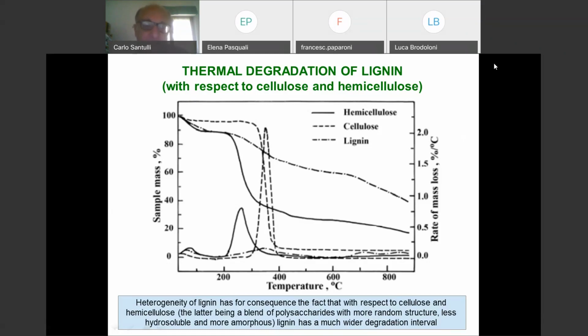So we start from 100%. Then we have some water. It dries, the first thing that happens, it dries up to 100 degrees or a little bit more, because then there is some sugary solution which can go away at a temperature which is higher than 100 degrees. At a certain point, it goes down. You have the onset of degradation. It might be faster, it might be slower, but in the end, it goes down to some amount of material which is left in the end. So basically, nothing is left from cellulose at 400 degrees. That's why, by the way, there is so much interest in burning paper. If it was just paper, which is not normally the case, you burn paper at 400 degrees, you have no ashes.